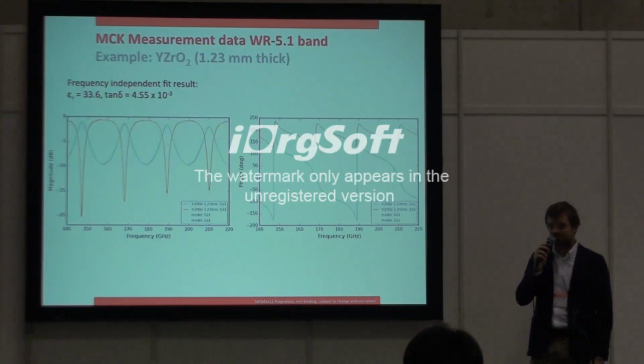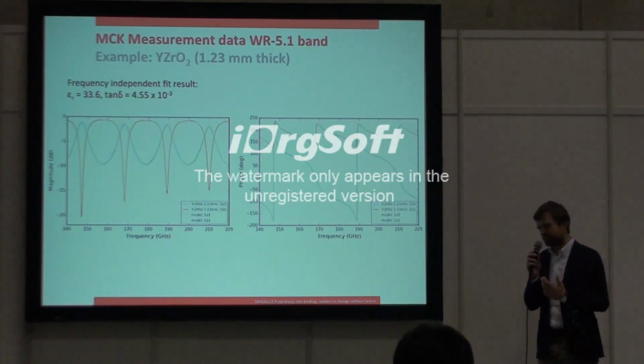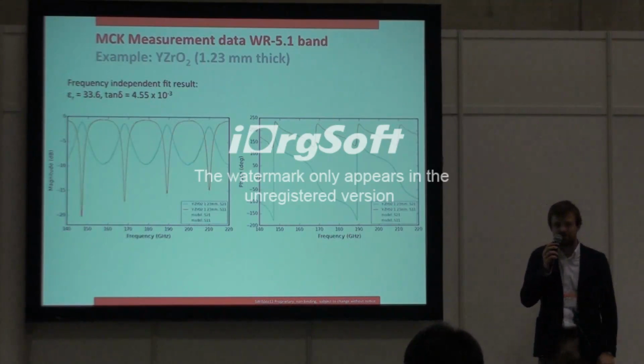I don't know if you remember a few slides before we showed yttrium-doped zirconium oxide between 500 and 750 gigahertz, and we saw that for that material we had a strong frequency dependence of permittivity. Now if we move down in frequency, we suddenly realize that that material no longer has a frequency dependence on its permittivity, which shows that at this millimeter wave and terahertz range, there is really a transition from a rather constant permittivity behavior as a function of frequency to a strong frequency dependence of permittivity. So typically now at 140 to 220 gigahertz, we're below the threshold for this material, where we have a constant permittivity behavior.